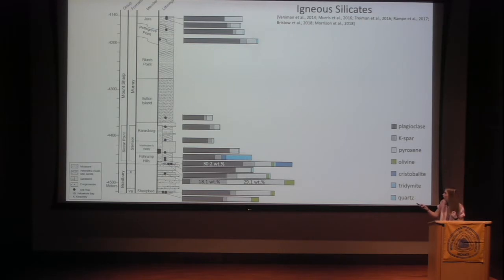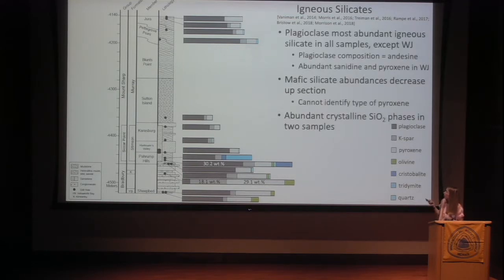So in this dark gray color is plagioclase, in the medium gray is potassium feldspar, light gray is pyroxene, green is olivine, this medium blue is cristobalite, this bright blue is tridymite, and these light blue, which we don't see much of, is quartz. Plagioclase is the most abundant igneous silicate in almost every sample, and I've labeled the highest abundances for each of these minerals just so you get a sense of how much is in here. But it's also the most abundant mineral, period, in almost every sample.